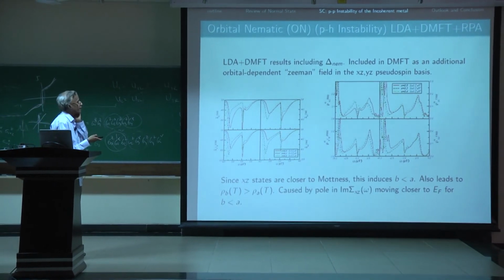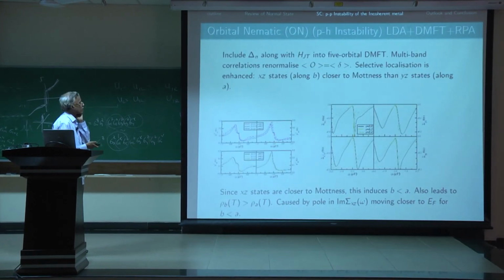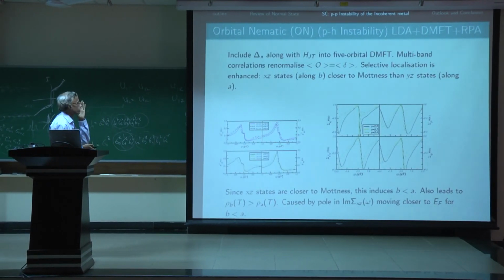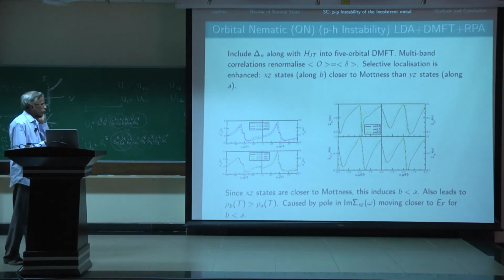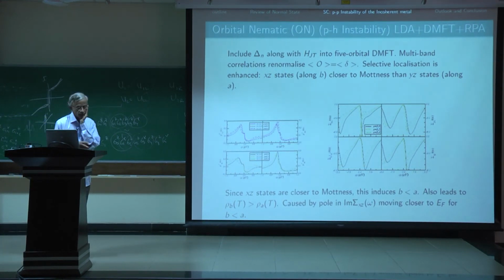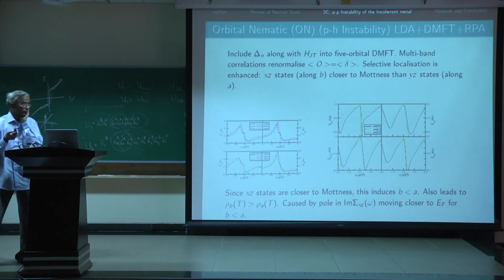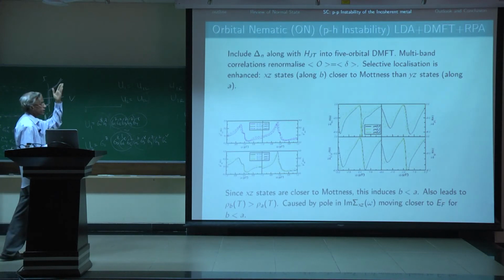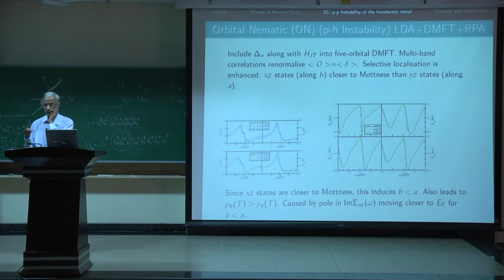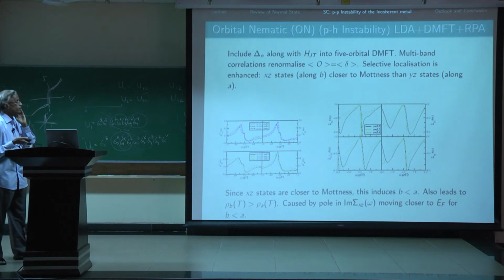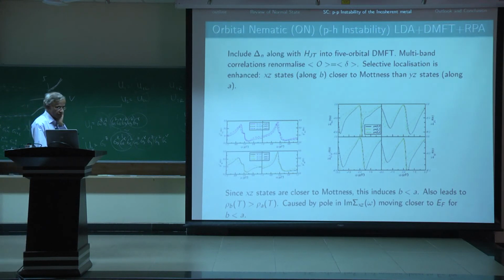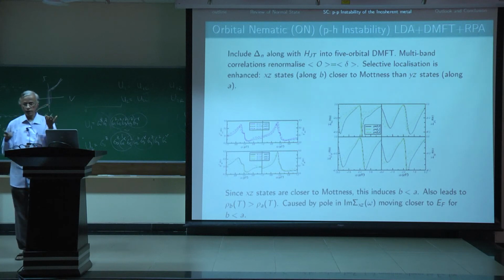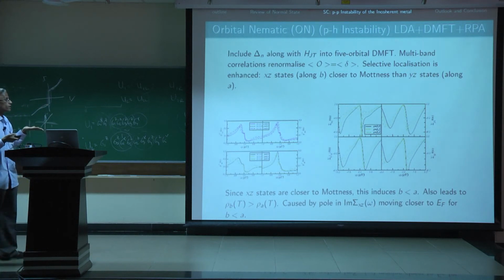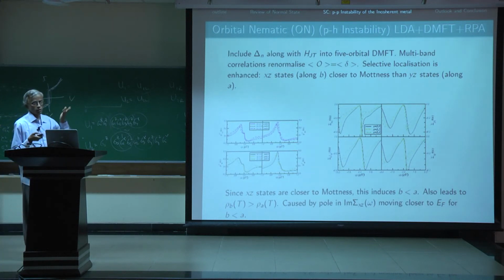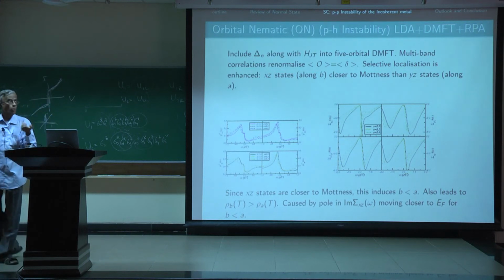So, in fact, this kind of accord motivates us to suggest that an orbital nematic order arising from ferroorbital order, which in turn arises from the residual interactions in an incoherent metal, is the main competitor to superconductivity in the iron arsenides. And antiferromagnetism arises once the structural distortion arising as a consequence of nematicity sets in.